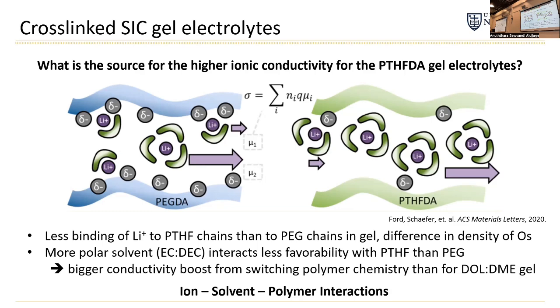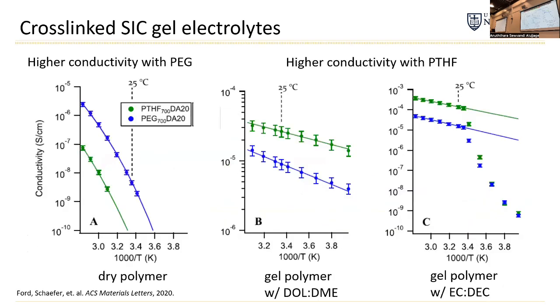The other difference that we noticed is if you look carefully in this data, you see that the magnitude, the amount of increase you get by switching out the polymer for poly-THF, is actually much better with a carbonate-based solvent. This was extremely confusing to us because the carbonate-based solvent actually has a higher dielectric constant, so it should be better at solvating. So then the question was, why does the polymer matter at all if this solvent is a better solvent?